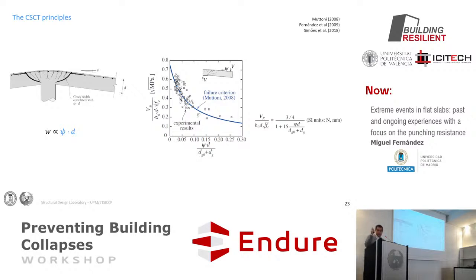When you are having long-term loading, this is something that I thought about with a colleague of mine, Eduard Faria, many years ago, but we never had the test to demonstrate it. But our idea is that, in fact, in your paper, the strain in the reinforcement is relatively constant. So it doesn't vary that much. There are some redistributions, but it doesn't vary that much. This means that if the strain in the reinforcement is constant, what's happening is that the compression zone is actually creeping, and this is making the slab turn, but this is not increasing the opening of the cracks. You see, the crack width is a block on top, or increasing a little bit, but then the neutral axis is also rising. So the opening of the critical shear crack remains rather stable, even if the rotations are not the same. I'm sorry, because this is a point that I saw while reading Sarah's paper.